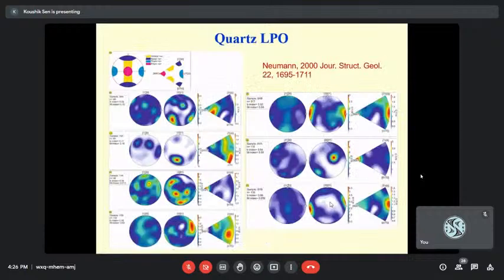Although we have done crystallographic LPO analysis for garnet also, garnet didn't really give us any meaningful LPO, so I haven't shown it here. Now, apart from omphacite, we also did it for quartz. For quartz, the most important and most interesting thing is that there are two samples which show the prism C slip, which basically indicates a high temperature condition, samples 8XB and 8YB.